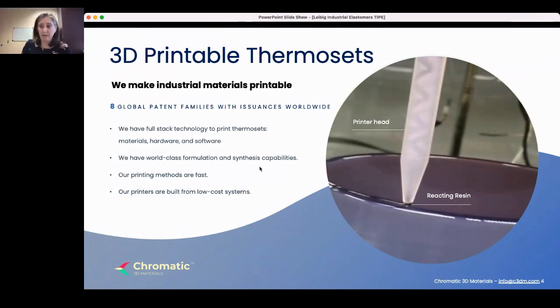At Chromatic, we synthesize our own materials. We have a lot of formulation expertise. And the other important element here is that the printing methods are quite fast, and we're able to build the printers from relatively low cost systems. The printing itself is conducted at room temperature, so very easy to have an open printing environment.